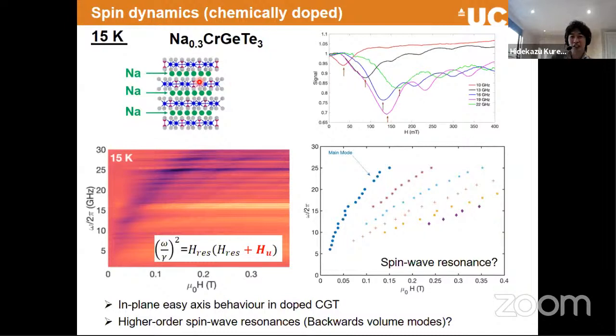One thing I didn't mention is that once it's doped by the alkaline atoms, it becomes air sensitive. So handling of this material is very difficult. That's something we really spent a lot of time on, but we managed to put this doped flake inside the cryostat without exposing it to air.